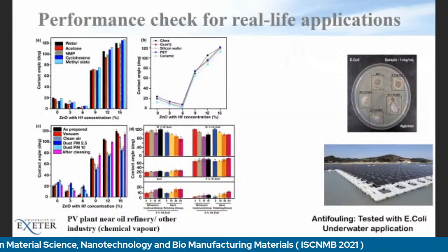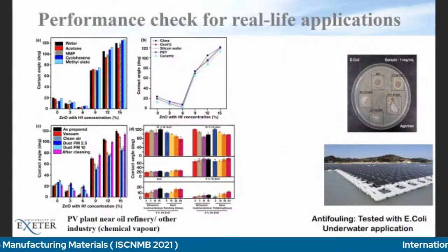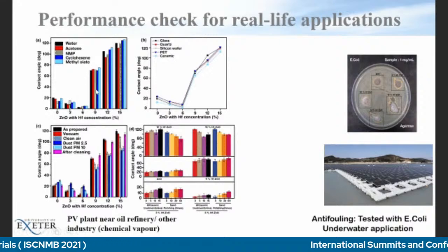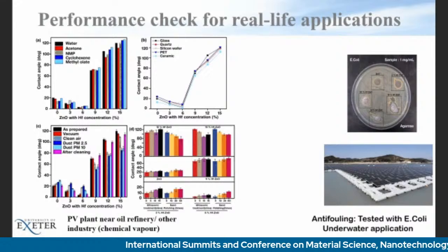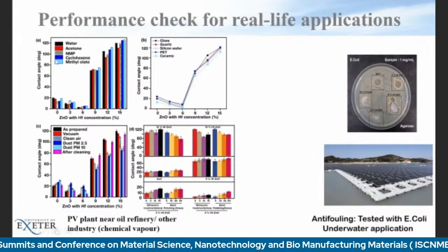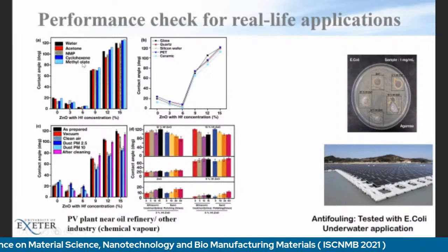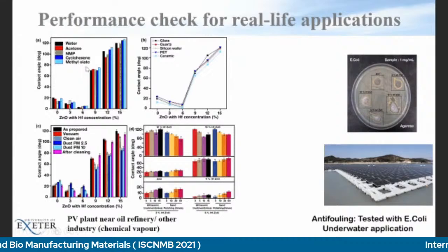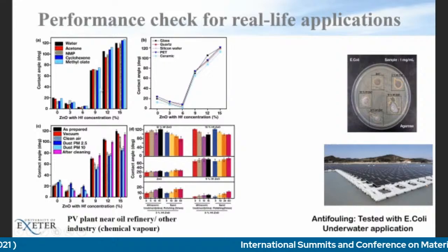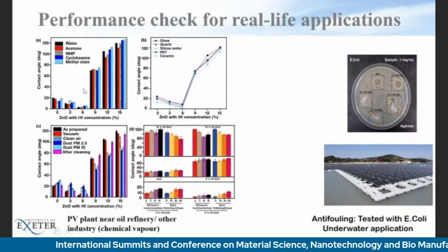Not only did we investigate the material aspect, but we also did some testing, because we know that the photovoltaic system can be placed anywhere globally, it can be a domestic application, it can be an industrial application. So we thought about how our coating system is actually having a good property. We tried with different other liquids such as acetone, NMP, and methyl oleate. We found that this material has very similar properties to water with the other liquids.